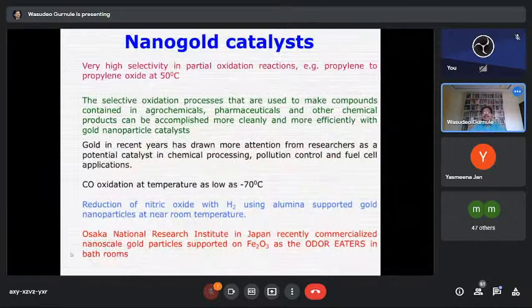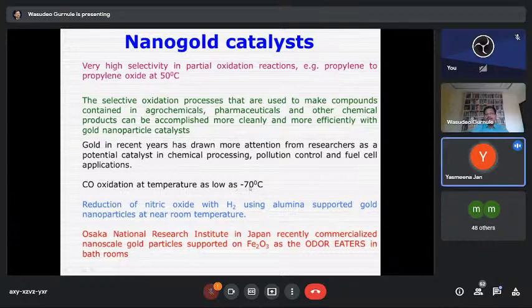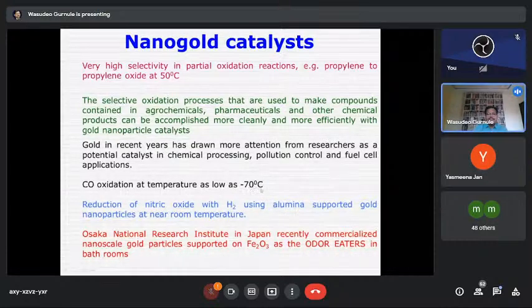This nano gold can be used as a catalyst because of the smaller particles and larger surface area. The larger the surface area, the better the catalyst. And here is shown carbon monoxide oxidation at a temperature as low as minus 70 degrees Celsius. For this case, this nano gold can be used as a catalyst.